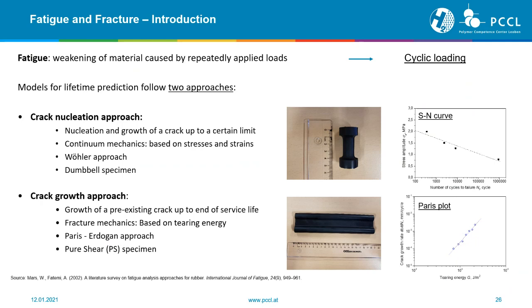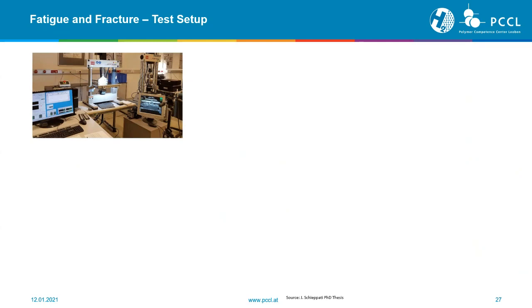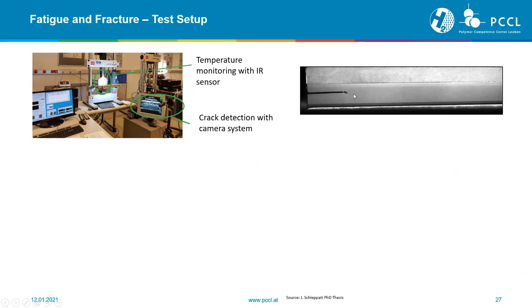It is more the fracture mechanics approach based on a tearing energy, explained by a Paris-Erdogan approach or Paris-Erdogan plot, using, for example, in this case, some pure shear specimens. For today, I'd like to focus a little bit more on the crack growth approach. I'd like to give you an insight into what we've done so far and what we have developed. You see here our test setup in the lab, where we have our specimen with an IR sensor and a crack detection system, so a camera, to monitor our crack growth over the number of cycles.